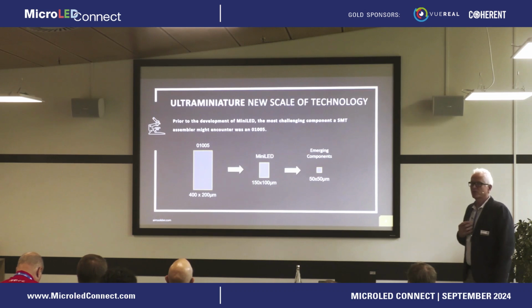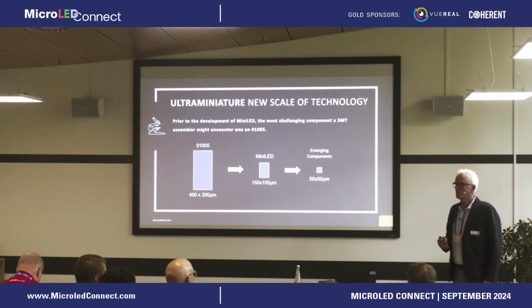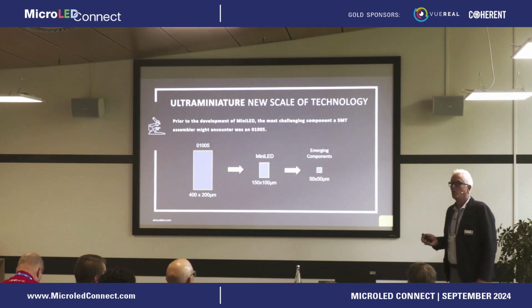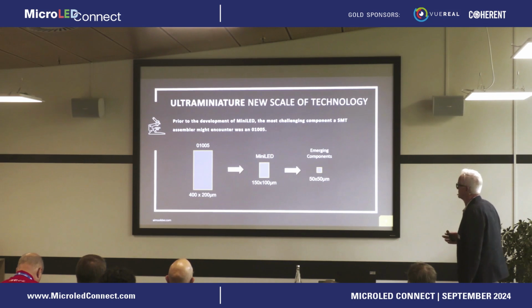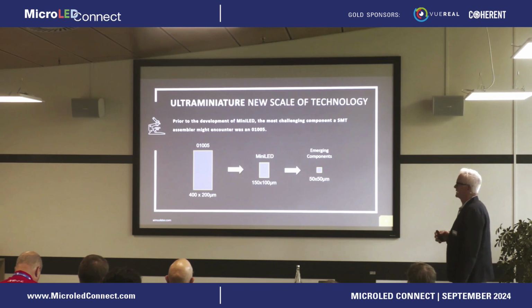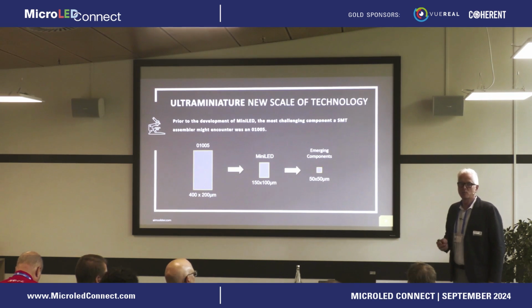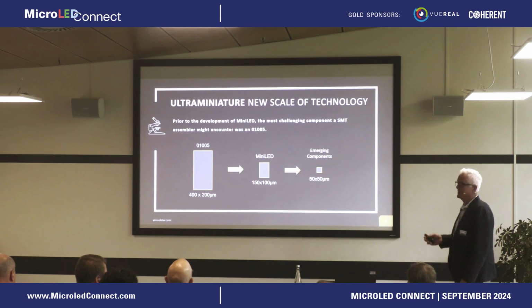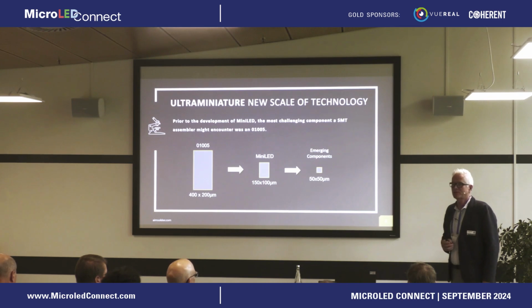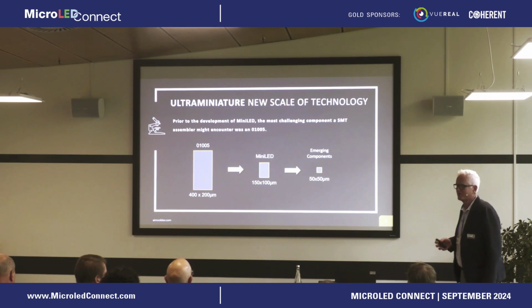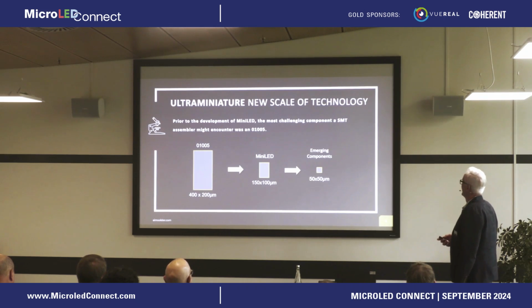So, I come from the surface mount world. We make circuit boards. And the smallest components that you would see in a traditional printed circuit board assembly are typically called 01005s. And they're about 400 by 200 micron rectangles. The application that we were successful in a production scale was using a mini LED that's about 150 by 100 micron. It was 4 times smaller than anything anybody had worked with in a traditional surface mount assembly line. And obviously, I thought 50 by 50 was incomprehensible, and now you guys want 5 by 5. Good luck. But here we are.